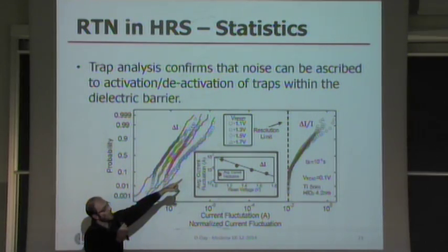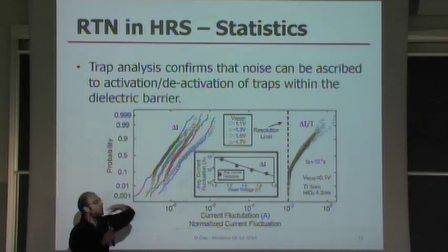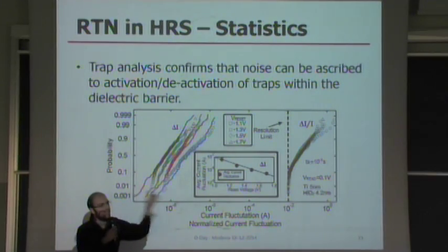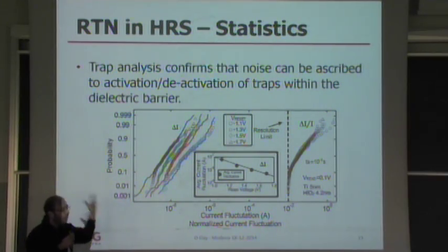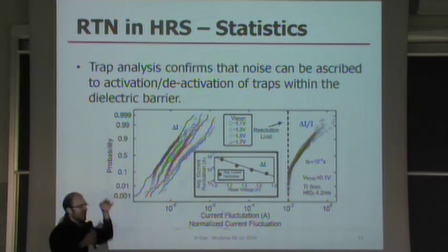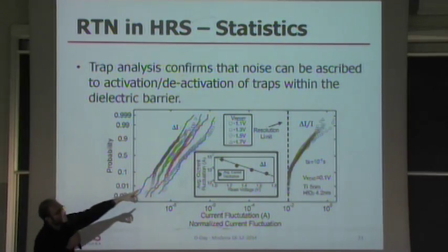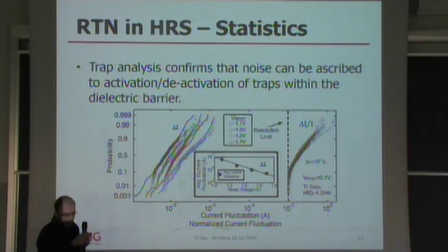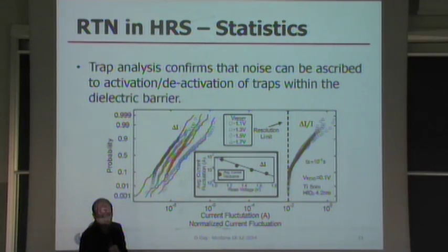As you can see, delta I over I, which is the fluctuation over the average value, is always the same, and does not depend on the barrier thickness. And of course, this is completely in line with the activation and deactivation theory, because the current step in this theory is actually the average current that the defect drives when it's active. Then it falls to 0. Every defect when it's not active falls to 0. That's why delta I over I seems to be constant in this perspective. So this is really in line with the activation and deactivation theory.